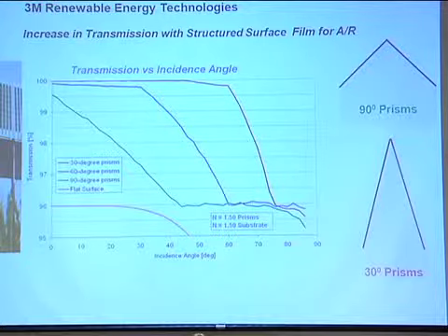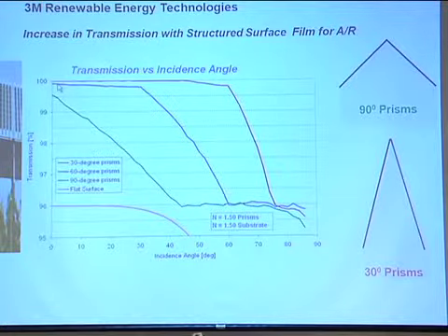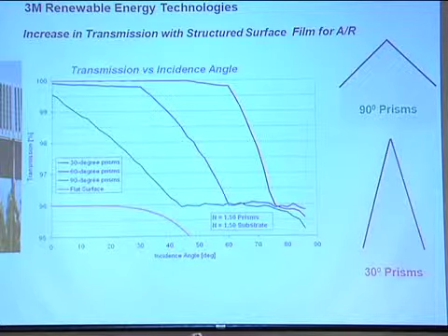And it's optical modeling that shows if you have, say, just a flat polymeric surface, you get 96% transmission at normal angles. But above 45 degrees, the transmission just drops incredibly. But you put these surface structures on there, and you can get 99.5, theoretically 100% of the light into the module. And even more importantly, off angle, at higher and higher angles, you capture more of that light. And this shows how the sharper the tip, the smaller the apex angle, the more light you can capture off angle.